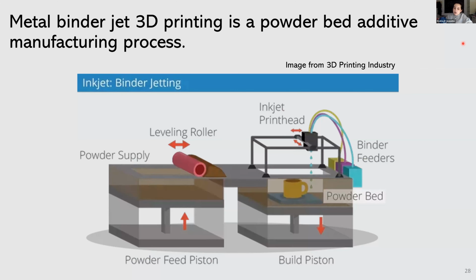So for those of you that are maybe not as familiar with additive processes, binder jet printing is essentially like a lot of the other powder bed processes, where you're laying a layer of powder and additively creating a three-dimensional shape. The main difference in binder jet versus something like powder bed fusion, where the powders are fused together using a high power laser, is that in binder jet we're using an organic binder that essentially just holds the particles together for now, and then you go through a secondary step of either sintering or infiltrating with a second material to actually bond everything together.